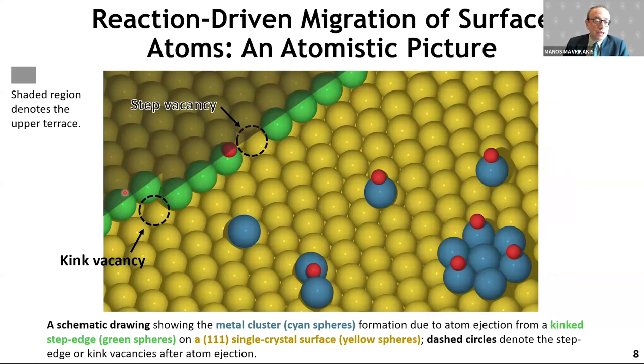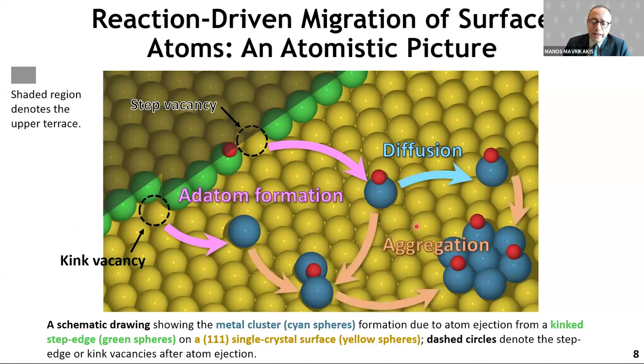I will show here a cartoon that shows you an upper terrace, a lower terrace of this copper 111 single crystal or any metal that we'll discuss. The green atoms represent the step edge, another step edge, where two step edges meet is a kink site. And then you have ejection of atoms from the steps or the kink sites. You form adatoms, these blue atoms, with or without an adsorbate. This red sphere represents an adsorbate. Then these ejected adatoms start diffusing on the surface. They meet each other and they aggregate. They generate dimers, trimers, etc. This heptamer, a nice structure here. So the idea here is to evaluate the energetics of each one of these processes, that is the ejection of atoms first, the diffusion, and eventually the aggregation towards cluster formation.